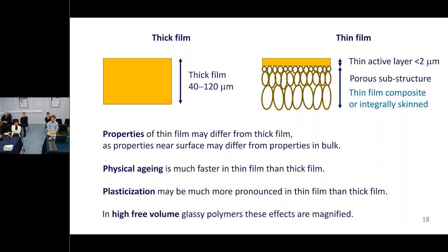And particularly because of the sorts of things I'm going to be talking about, it's all about the conformational flexibility, how much freedom there is for the polymer. There's more near the surface, and so things are different in a thin film to the thick film. And so we actually need to learn a lot more about what happens when you get to these really thin films, which isn't always the same as what happens in the thick film. I mentioned physical aging as being one of the things we have to address. That is much, much faster in a thin film than in a thick film.